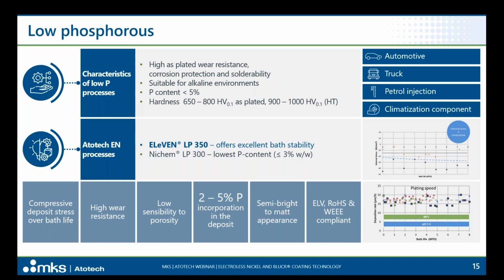As we can see on the right-hand side on the graph, we have compressive stress over the bath life, which is very good regarding adhesion and corrosion protection. We have a high wear resistance and a low sensibility to porosity. And regarding appearance, we have semi-bright to matte coatings. All these processes are compliant with the regulations on the market, ELV, RoHS, and WEEE.